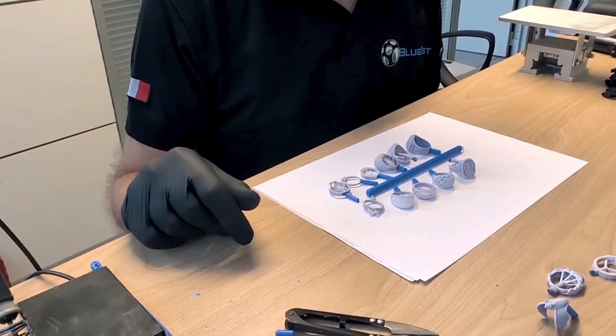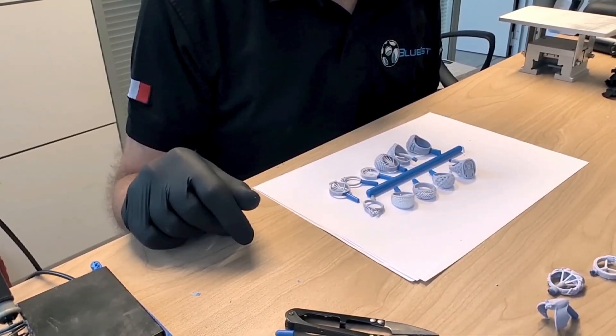Standard rings and classic models can be mounted halfway up the sprue, and the larger ones should be placed near the metal entry cone.